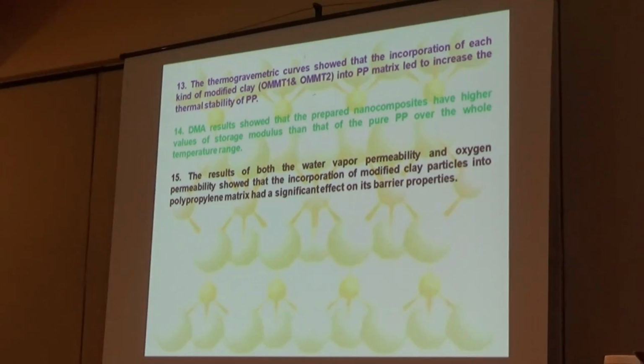The thermogravimetric curves show that the incorporation of each kind of modified clay into polypropylene matrix leads to an increase in the thermal stability of polypropylene. Dynamic mechanical analysis results show that the prepared nanocomposites have higher value of storage modulus than that of pure polypropylene over the whole temperature range. The results of both the water vapor permeability and oxygen permeability showed that the incorporation of modified clay particles into polypropylene matrix had a significant effect on its barrier properties.